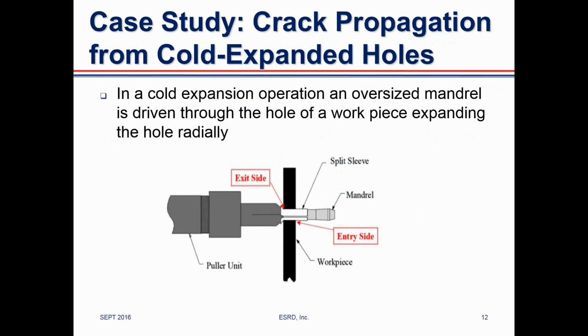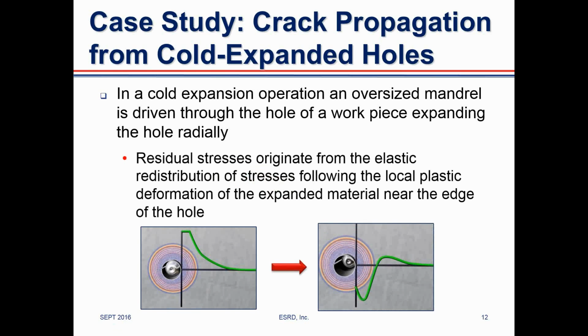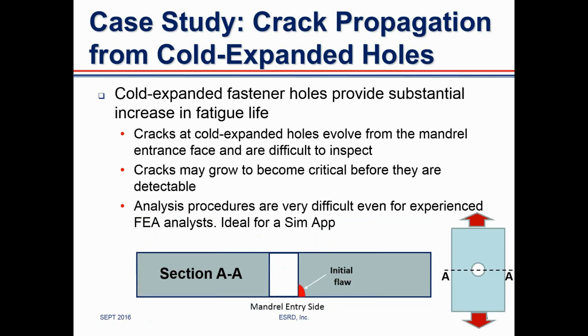What I'd like to present in more detail today is a case study of crack propagation from cold expanded holes. For those of you who are not familiar with the concept of cold expanded holes, a cold expansion operation is simply inserting an oversized mandrel, as indicated here. The black object here represents the workpiece. This is a mandrel that is inserted into the hole with a sleeve, and when the mandrel is driven out of the workpiece, the part deforms radially, and residual stresses originate because the elastic stress distribution following the local plastic deformation of the expanded material near the edge of the hole compresses the plastic zone, creating a state of residual stresses as indicated here. The significance of this residual stress field is that cold expanded fastener holes provide substantial increase in fatigue life by reducing the rate of crack propagation that may initiate at the hole.